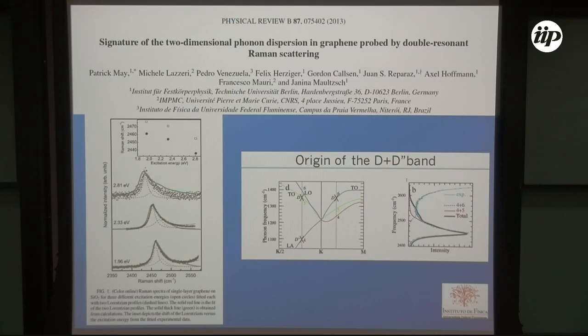So here we have my calculations in green. We have an impressively good agreement. I must secretly tell you that in this case we have some cancellation of errors, and that's because when the agreement is so perfect, that happens to any theoretician. So be careful. If your agreement is so good, you need to be suspicious. In this case, we have some cancellation of errors. But anyway, we can explain exactly the origin of this band that we today call D plus D prime prime, because it's a combination of these two phonons.